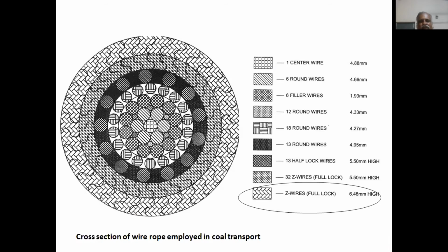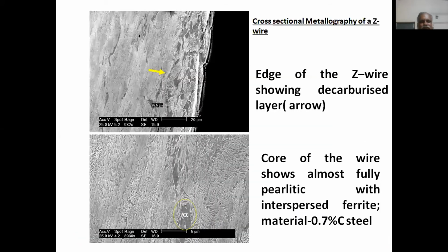If you look at the cross section of the Z wire, it's basically a 0.7% carbon steel. What does that mean? You know, 0.8% is 100% pearlite. 0.7 means 0.8 minus 0.7 divided by 0.7. How much is that? About 1/7. 1/7 will be ferrite presence. So you find that 1/7 is ferrite stringers with pearlite, the rest, or 6 by 7.